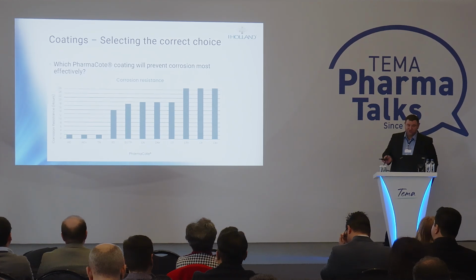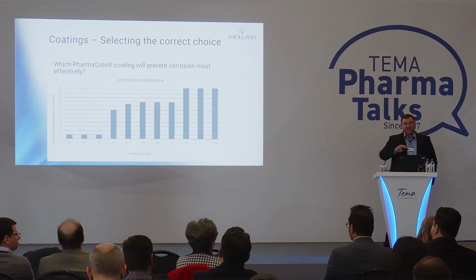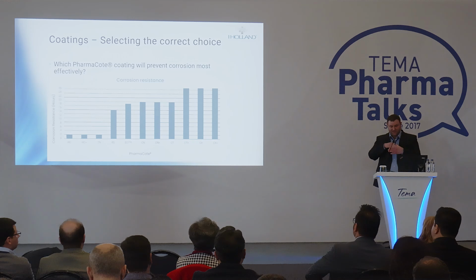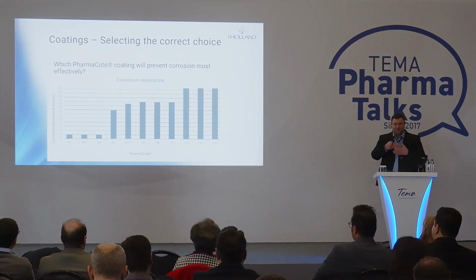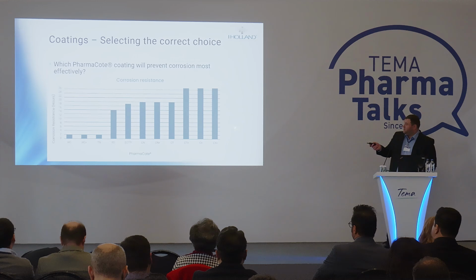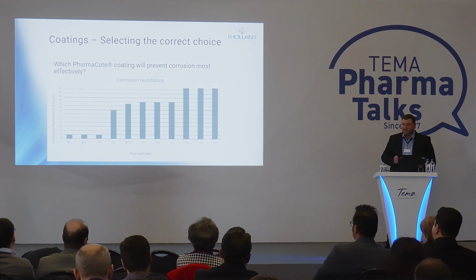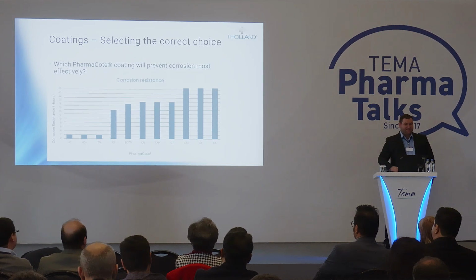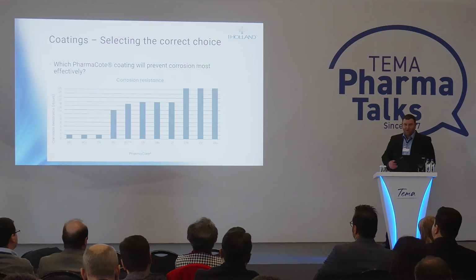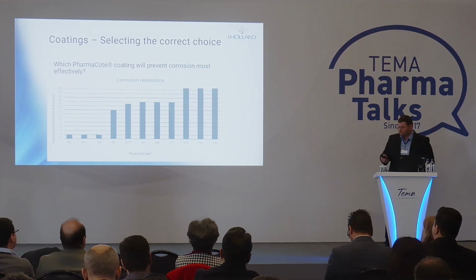So hard chrome, 2 hours. After 2 hours, we already see corrosion, and that gets back to that plate form that you see on the surface. Because you have the plates, you have the boundaries in between them, and that's where the corrosion starts to form. The PVD coatings, because they're much more even, much more consistent, and have better structure, we do not see that corrosion form straight away. The coatings that demonstrate the best corrosion resistance, as you would perhaps expect, are our thicker applications of those coatings. So CN and CX chemically are the same coating, have the same hardness, but CX is a thicker version. So it takes longer for that corrosion to take effect. They also last longer as well.